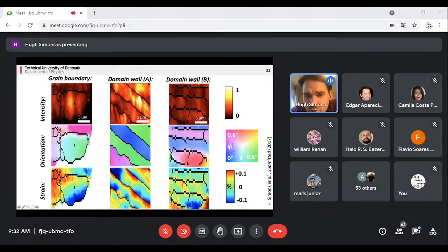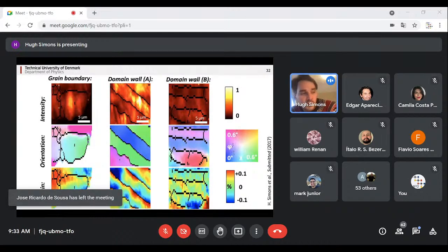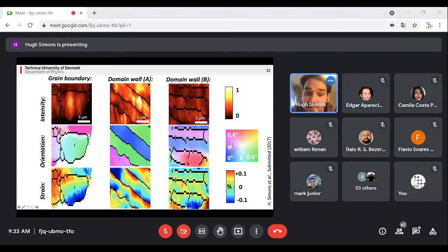And this is a really big issue because these strain gradients break the lattice symmetry. Because the material is subjected to these strain gradients, it also fundamentally changes the electronic and the functional properties of these materials. And all of our current theory is based on the fact that all of these should be unstrained. If you look at the fundamental theory for domain walls, DFT in particular states that the size of these domain walls should be very small, on the order of a few nanometers. But what we show here is that, in fact, their effects are much, much longer ranging, more along the scale of tens of micrometers.